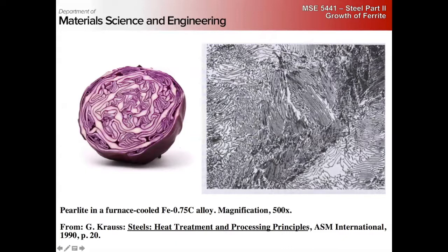It's really these plates. It starts from a point, nucleates out in a sphere in these layers, so it's like layers on an onion. But of course, they can branch and do all kinds of stuff, so it's really more like the leaves of a cabbage. When you look at it in a 2D cross-section, it's hard to imagine what the structure actually looks like. But these are 3D plates that are bent around each other in this complex, largely equiaxed spherical arrangement, right?